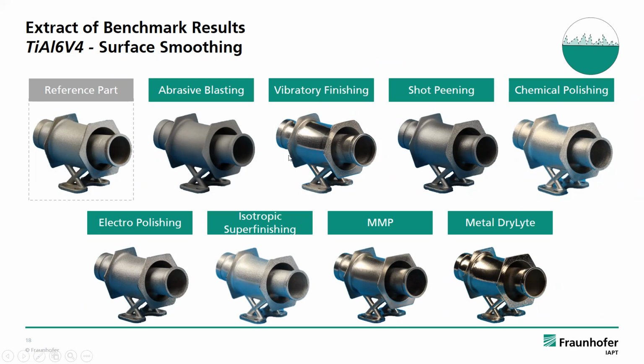I think it gives a high value insight on the influence of these finishing technologies here on surface roughness, penetration depth, edge rounding, and so on. So you will get a 120-page report dedicated to the influence of different surface finish on these three materials here. And here, just as a teaser, you can see the appearance of our demonstrators for titanium 6.4. I think in general, finishing is one aspect to consider from the very beginning of the process chain. The part isn't ready when printed, as you all know, and we are working towards integrating finishing procedures on the metal side and on the polymer side into our processes, providing you integrated AM solutions.